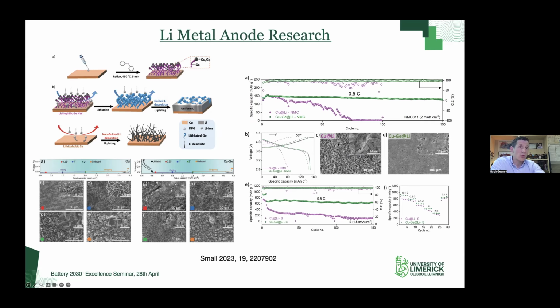And this is the post-mortem analysis of the plating morphology at the anode side. This is, again, very uneven. We would have dead lithium that would not be reversible in the case of the copper alone. And on the right-hand side, when we have our germanium included, we're able to, again, really regulate that lithium stripping and plating characteristic.